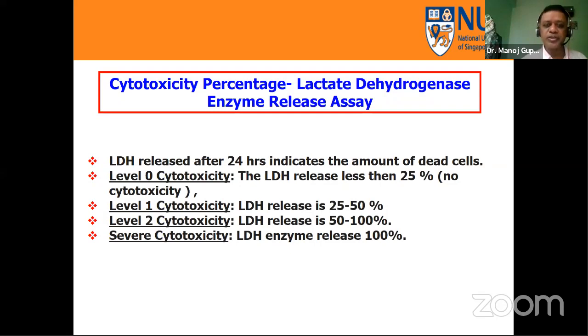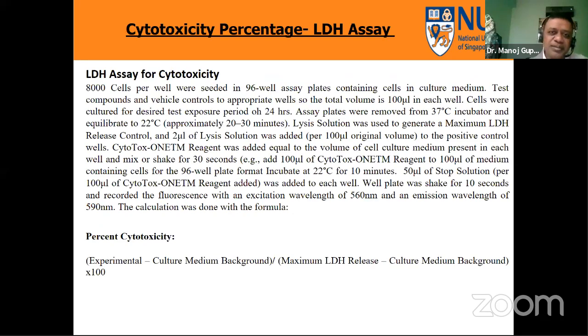From LDH release, they define level 0 cytotoxicity if release is less than 25%. If it's between 25 and 50%, that's level 1 cytotoxicity, level 2 is 50 to 100%, and severe cytotoxicity is at 100%. So basically you want level 0, but level 1 is acceptable at lower numbers like 25 to 30%. These are the details of how they did it.